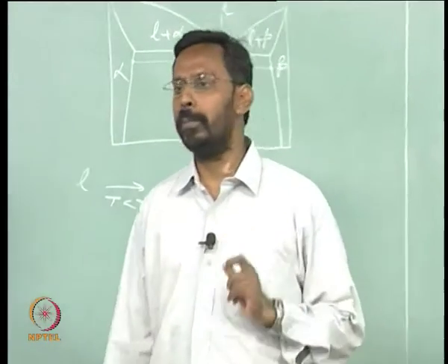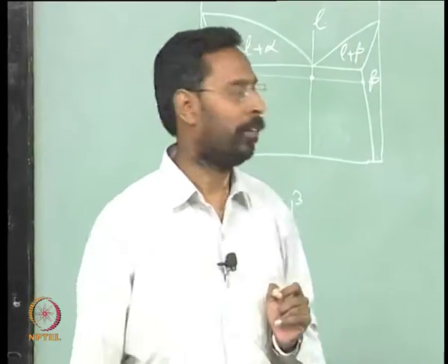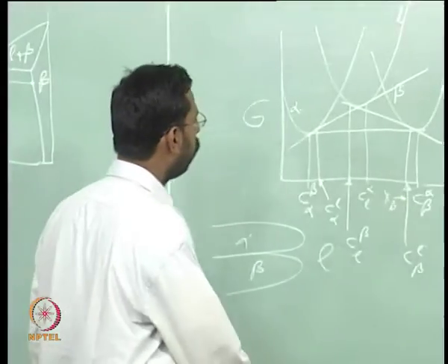What am I getting out of all this? Just simply six compositions we have got. But if I carefully observe these six compositions—forgetting about the first two between alpha and beta—look at these four compositions. If I compare the composition of liquid in equilibrium with alpha and the composition of liquid in equilibrium with beta, I get some information. What is the composition of liquid in equilibrium with alpha?